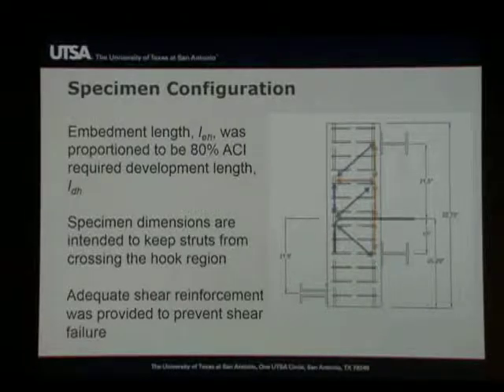We went about designing the specimens. We wanted to have a hook failure. We didn't want the bars to yield, and so we use as a reference the expressions in the ACI code. And we started by proportioning the length of these hooks to be approximately 80% of what those would be. And by the way, those would be the same expressions that are in the AASHTO code for the development length of hooks.